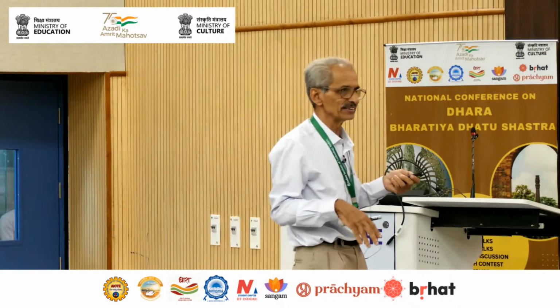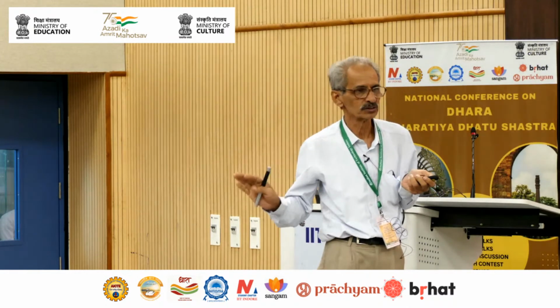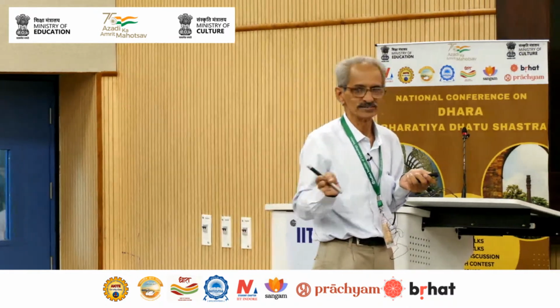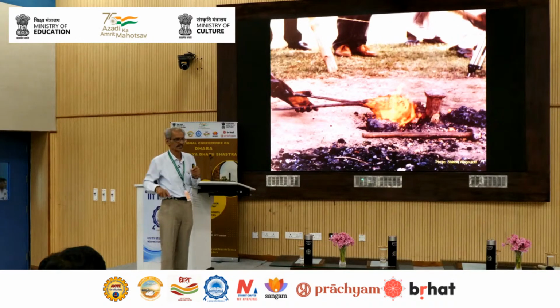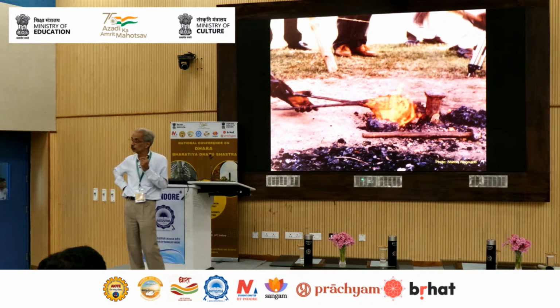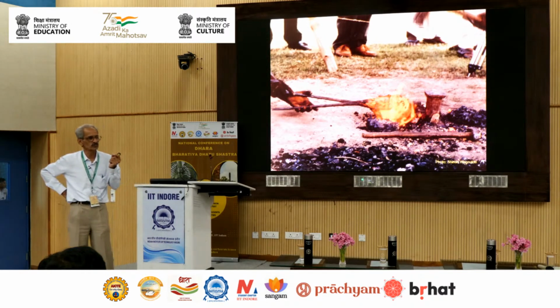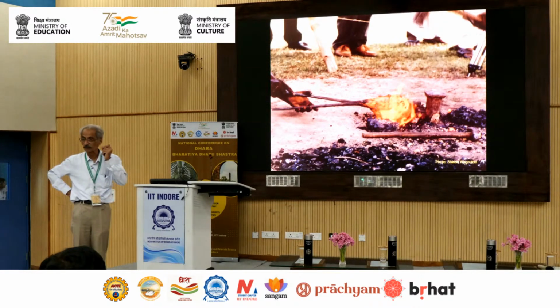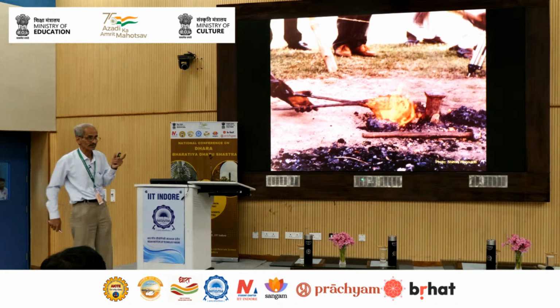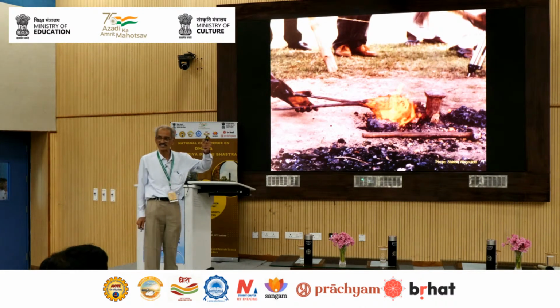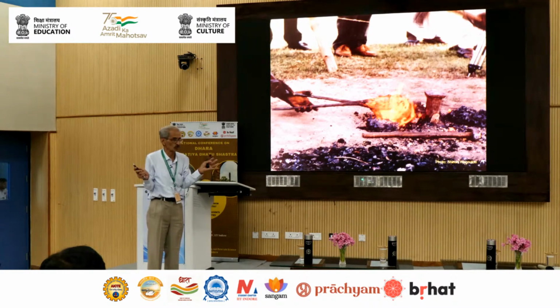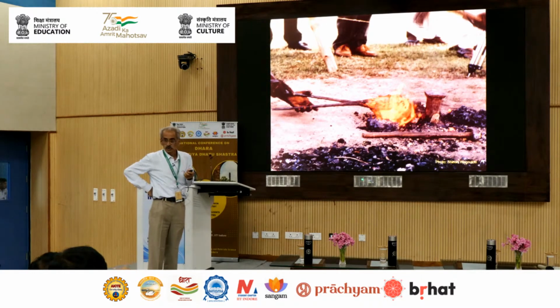If it's too low, then the slag is also not molten, so you can't squeeze it out. Then you just put one hammer on top, it will break into pieces, which used to happen most often to us in IIT Bombay. Or iron will melt, and if the iron melts, it is catastrophic. They don't want the iron to melt, and you know why? Because as soon as the iron melts, it will pick up all the other things. It will pick up silicon, manganese, it will pick up everything else. So you don't get that quality of iron if it melts. So the Chinese always melted, but then they cast it. It is not forged material. But your temperature is not very high here to melt the iron.